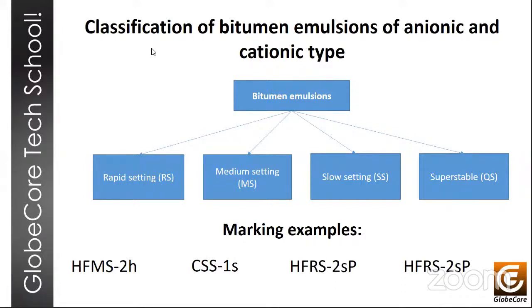For some brands of emulsions, we also use letters H or S in the designation, indicating solid or hard bitumen for H, or soft for S. For some types of anionic emulsions, we can have letters HF in front, which means the addition of special agents to the emulsion, giving it the property of high flotation, so the emulsion creates a thick bitumen film on the mineral material.